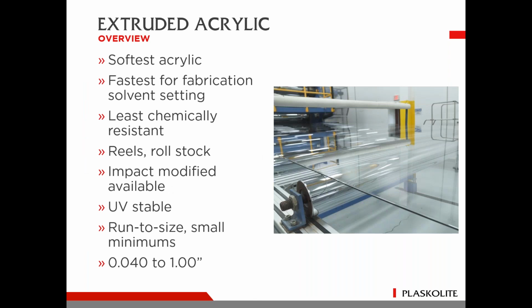So from the extruded side, the extruded, if you want to call it, would be the most ductile or the softest surface finish. It would still be higher hardness than polycarbonate or PETG, but compared to cell cast or continuous cast, it would be the softest acrylic. It does have a very good way of solvent setting for fabrication, so it's the fastest setup. Due to the fact that it's the least chemically resistant, when you put a bonding agent on it, like Weld-On or something like that, that would chemically bond the substrate to itself, that can attack it quicker because it's less chemically resistant.